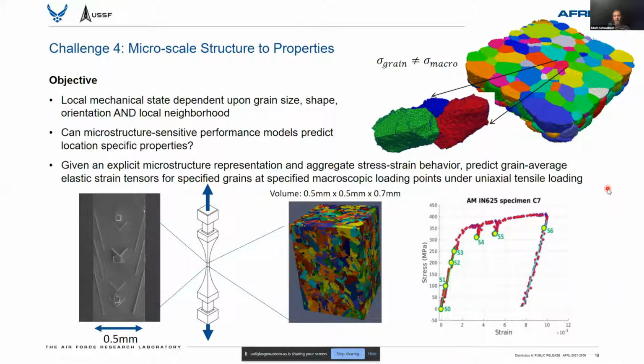This can be pulled in tension, and you can see on the right here a stress-strain curve with some interrupted experiments collected along the evolution of this stress-strain curve for this specimen, where we performed at each of these yellow points a diffraction experiment, a near field and far field diffraction experiment that allows us to characterize the microstructure to some extent, but more importantly, the state of strain in the individual grains in this specimen. So we can see basically how the aggregate loading of the specimen is partitioned in various different grains, to get at the effect of not just the details of a particular grain's description, but also its neighborhood, what grains surround it.